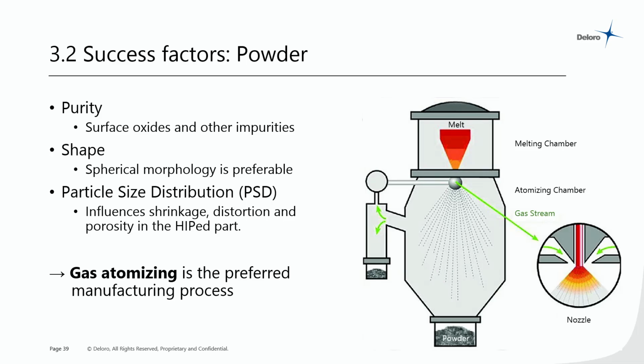Shape is important. Generally, provided it's possible, a spherical powder is preferred because the packing density of a spherical powder is generally better. And the particle size distribution is also important so that the tap density of the powder is as high as possible so that we can get as low as possible shrinkage and distortion. Therefore, because of all of these reasons, gas atomizing, which is shown schematically on the right, is actually the preferred process for HIP powders, particularly for metals and alloys, basically provided one can gas atomize the material that we're HIPping, of course.